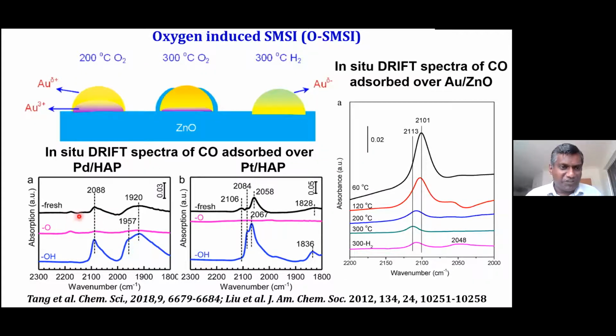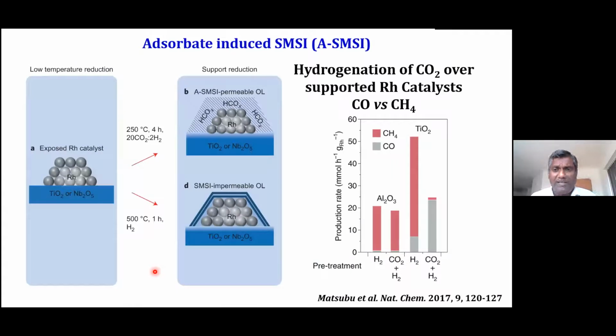For example, here it's the fresh catalyst. This is the CO adsorbed. You can see the CO adsorbed peak. When you oxidize this sample, you can see there is more or less no adsorption of CO on the gold site. But when you hydrogenate this oxidized sample, you get your CO adsorption back. So this is what is called oxygen-induced SMSI, or O-SMSI. To the best of my knowledge, these two are the reports of this oxygen-induced strong metal support interaction. Very recently, a group led by Christopher et al. reported something called adsorbate-induced SMSI.